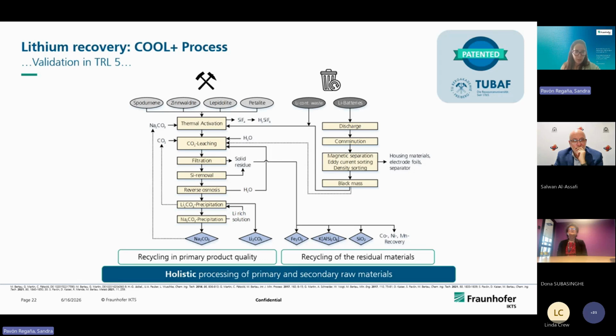Now I want to present the COOL+ process, a holistic processing of primary and secondary raw materials. So we can tackle and mobilize lithium coming from primary sources, like spodumene, zinnwaldite, lepidolite, and petalite, as well as lithium-based material, that means from the black mass. The pre-processing obviously is different, so we cannot do the pre-processing the same for primary and secondary.